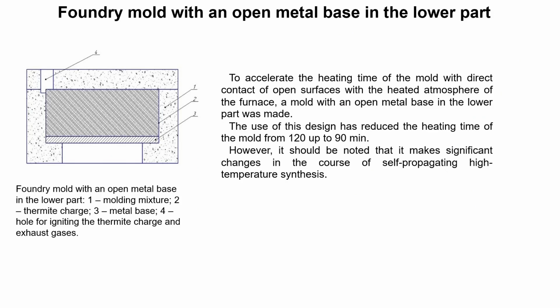To accelerate the heating time of the mold, with direct contact of the open surface with the heated atmosphere, a mold with an open metal base in the lower part was made. The use of this design has reduced the heating time of the mold from 120 up to 90 minutes. However, it should be noted that it makes significant changes in the course of self-propagating high-temperature synthesis.